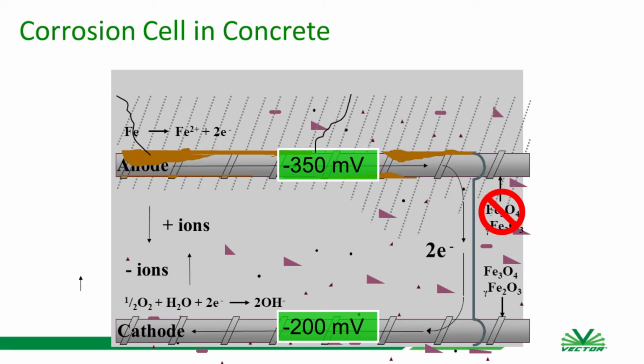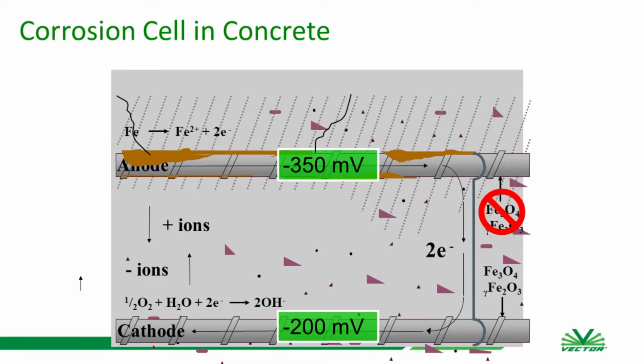The cathodic area will accept those electrons, and then hydroxyl ions will go back and forth through some type of electrolyte. Well, in concrete, that's our electrolyte. If we were working in pipelines, the soil would act as our electrolyte. In marine environments, the water. Those hydroxyl ions go back and forth, then you get Fe2O3, or rust byproduct, or corrosion byproduct, that forms around your steel. And that's what can expand up to 10 times its natural size, and that's where you're getting your cracking, your spalling, all those nasty things that happen to our structures.